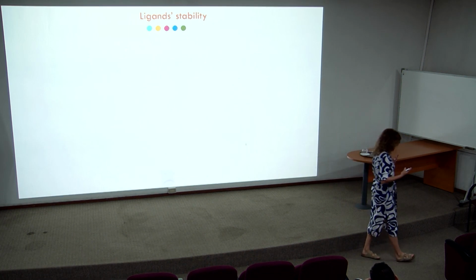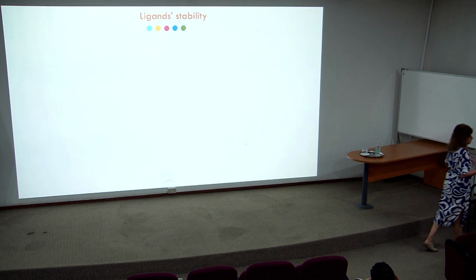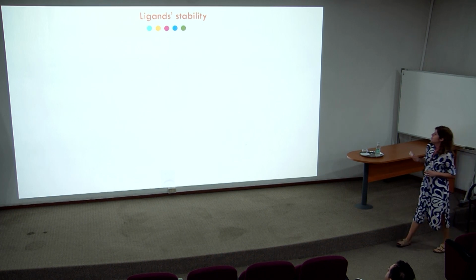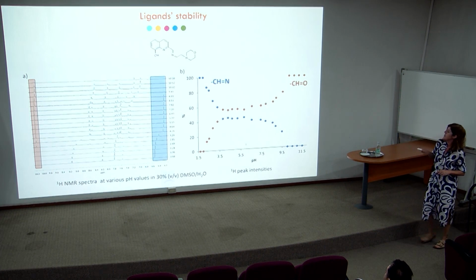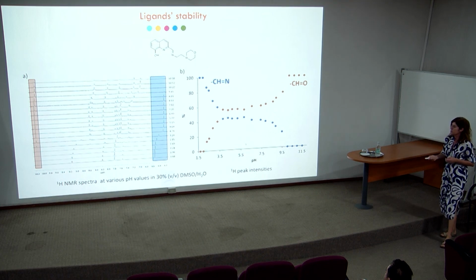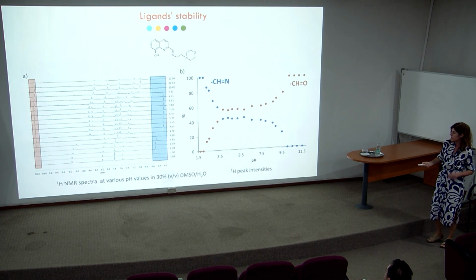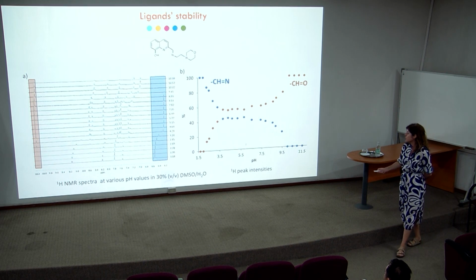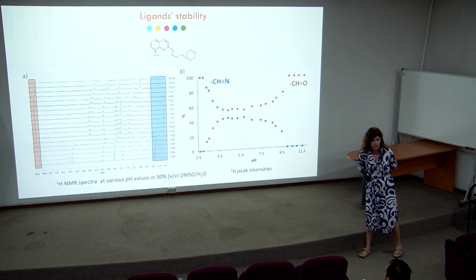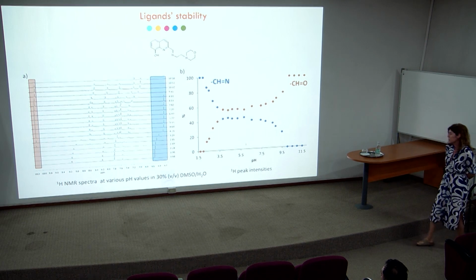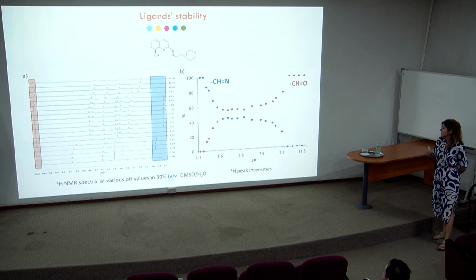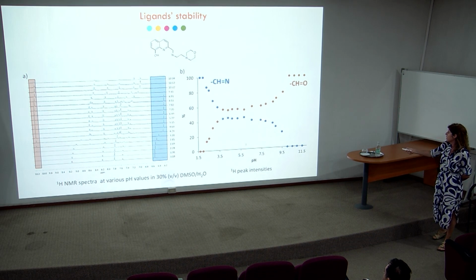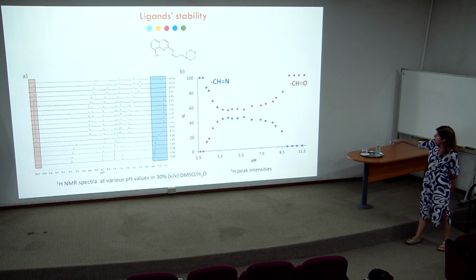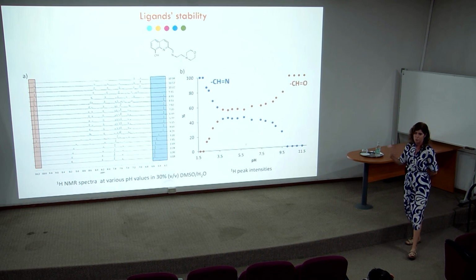So these ligands are Schiff bases. I think some of you know that Schiff bases are prone to hydrolysis, so it's easy for the ligand to revert to its original reactants. And we could observe that this happens with these ligands. So this is the NMR spectra at various pH values in a solution containing 70% of water, 30% of DMSO to solubilize the compounds, and we could identify the peaks belonging to the imine, which decreased with the pH, and the peaks belonging to the aldehydes that increased with the pH.